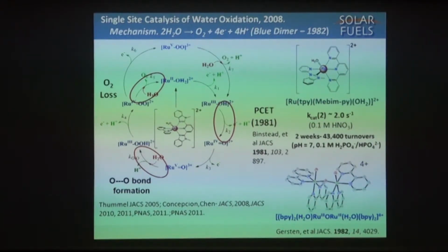And then something else emerges that we didn't know anything about before, called proton-coupled electron transfer. Look at what happens here. Here's an aqua, it oxidizes, but the pKa of that water group, if you do a titration, is typically 9 to 10 in these complexes. Once you oxidize to ruthenium-3, depending on the coordination environment, the coordinated water becomes much more acidic. So at any decent pH, ruthenium-3 is now a hydroxy form. When you go to ruthenium-4, the characteristic coordination sphere is to have an oxide group with real multiple bonding between the ruthenium and the oxygen. What's happened is that as the metal gets electron deficient, the OH protons become more acidic. When they leave, they open up p electron density for donation back to the ruthenium. That is a key because with the oxide group, it opens up reactivity channels that are well known: oxygen atom transfer to phosphines or sulfides, and as we'll see in a moment, to water molecules.